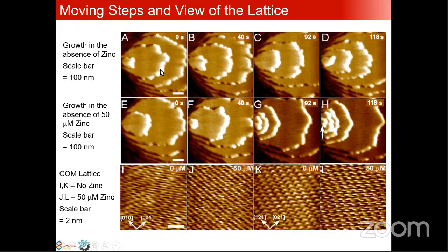You have the almost triangular growth pattern emanating from the dislocation center. Now, in the presence of 50 micromolar of zinc, what you will see here is that it started to have step bunching at G and H, and then it slowly changes into circular step shapes. As a bonus, we also tried to image the lattice, the way the atoms are arranged, and whether they would be influenced. We see some slight change, for example, I and K have no zinc, and J and L show you the presence of zinc. There's a little bit of a change in the lattice, but we couldn't really assign the atoms here. It would require another study that would have to work on the molecular modeling aspect as well.